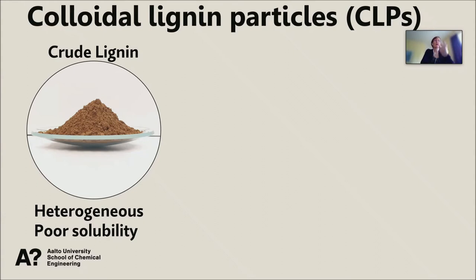I haven't added the chemical structure here, maybe I should have, but the chemical structure is very much dependent on the biological source of lignin and also on the process from where it's taken. When we do pulping, for example, the focus is to get the cellulose fibers as intact as possible, and we don't care about the lignin. So chemical reactions happen in the lignin, which makes it a bit smelly and also more difficult to use.